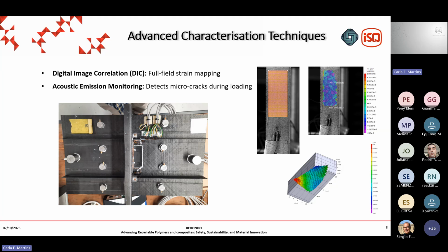Unfortunately, I did not have the application of the method for a laboratory specimen like we are talking here. So this is a sort of small component that we tested some time ago for some work, in which we have an array of acoustic emission sensors. By knowing the locations of those sensors and the distances between them, we can, with some analysis software, identify precisely when fracture starts, so when the material starts to break and produce some characteristic noises that can be identified, and the physical location of that initiation, where it started physically.